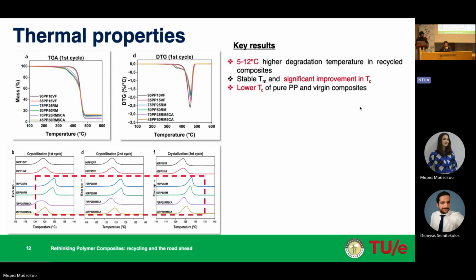So the rate of crystallization happening in the recycled composites was quite good compared to the virgin composites. As we can see here in the graph, we can literally see the big shift happening in the crystallization temperature compared to the virgin composites.